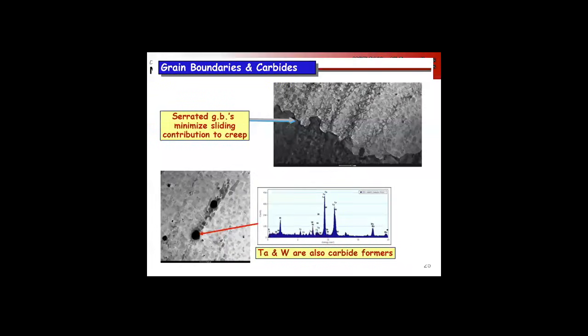Okay, so grain boundary carbides. One key thing that we see about the grain boundaries in a lot of the disc alloys is this serrated, tortuous grain boundary path. The lower energy we can make the interface, the less straight it has to be - the less energy there is associated with curvature of the grain boundary.